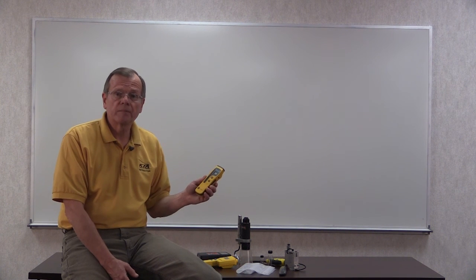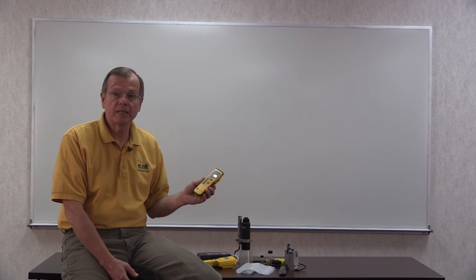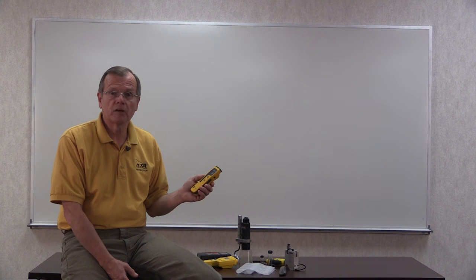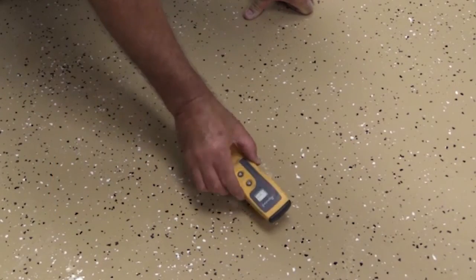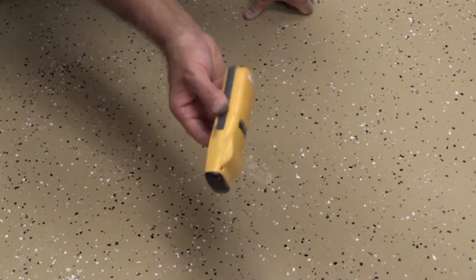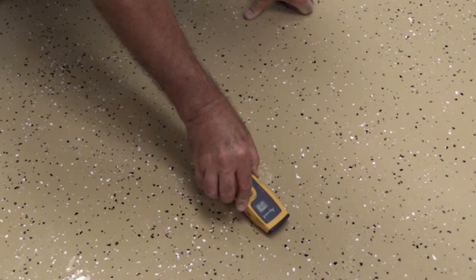This is a radio frequency meter. To take readings with the radio frequency meter, hold the gauge along the black strips on the sides and make certain there is two-point contact with the surface. Press the button to take a reading. The results are depicted on a relative scale from zero to 999 as well as a colored light indicator. You want two-point contact with the front of the meter and this little raised area — put it on the surface and you get a direct readout of moisture content.